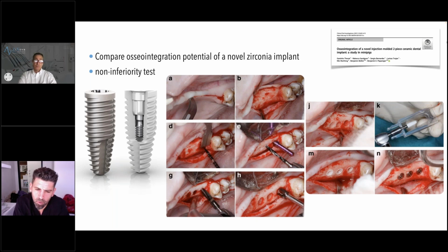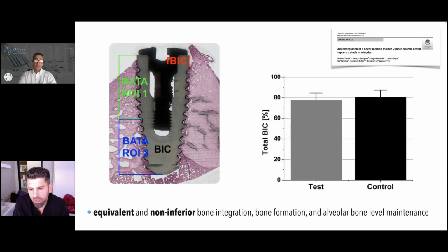This was in an animal model. This was mini pigs, and you can see from the surgical photographs, they placed 3 implants, titanium, and 3 zirconia. And just to simplify, they saw at the end that the ceramic implants manufactured by injection molding were equivalent and non-inferior with respect to bone integration, bone formation, and alveolar bone level maintenance when compared to titanium. I mean, it is clear, again, that these implants integrate well, they're able to maintain bone, and there's absolutely no difference with titanium implants.